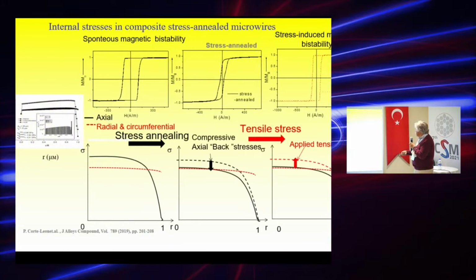And now to understand this behavior, this is spontaneous magnetic bistability in the as-prepared sample. In this case, I just reproduced this schematic picture. The axial stresses are almost the highest across the whole diameter. Now, if we subject these materials to stress annealing, because of back stresses, which is one of the origins of this stress annealing induced anisotropy, we make the axial and radial stresses almost similar.